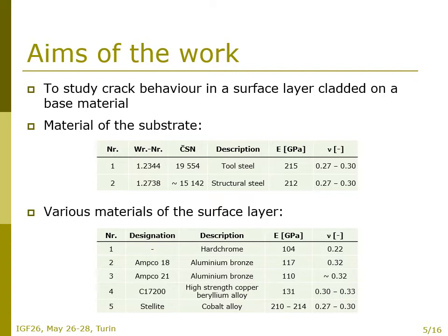The main aim of the work presented is to study crack behavior in a surface layer cladded on a base material. Several combinations of layer and substrate material properties are considered. As the material of the substrate, two kinds of steel are considered: a tool steel and a structural steel, with the presented elastic properties, Young's modulus and Poisson ratio. As the materials of the surface layer, the following can be used: hard chrome, two kinds of aluminium bronze, high strength copper beryllium alloy, and a cobalt alloy. And you can see the elastic properties again.